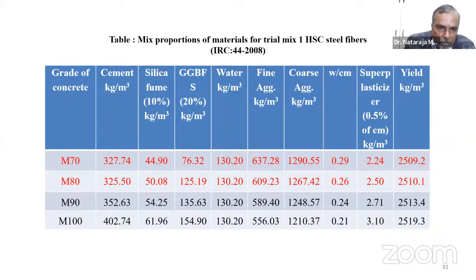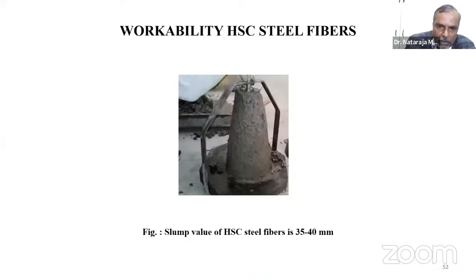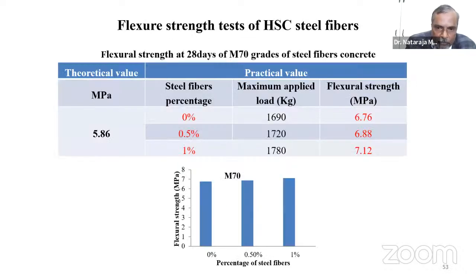And just to tell you, it's the same mix design. In fact, we have just added the fiber at different proportions. And this is where the workability decreases. In fact, if you add the fiber, I'm still getting about 40 against 75. But now we should put an additional 0.25 dosage of chemical. Again, your workability will increase to something like 75 mm or so.